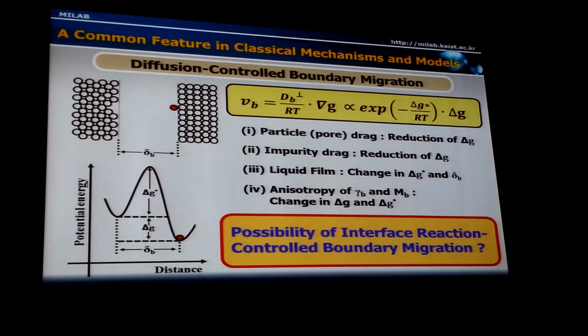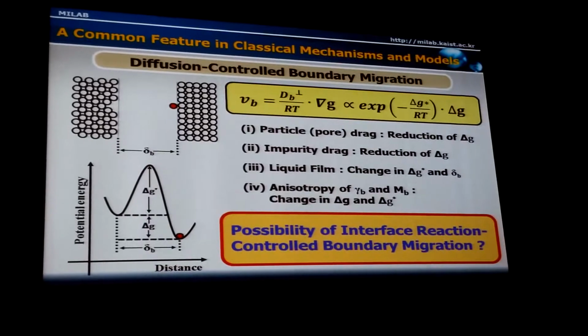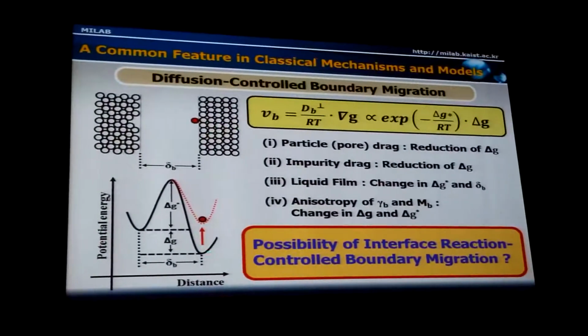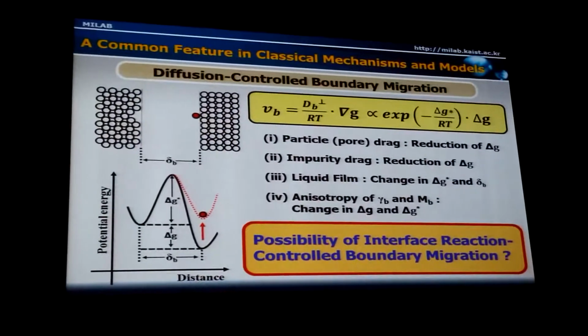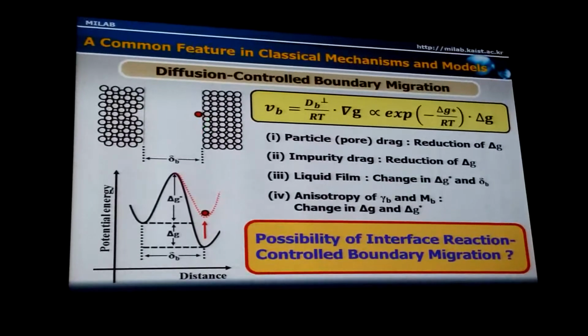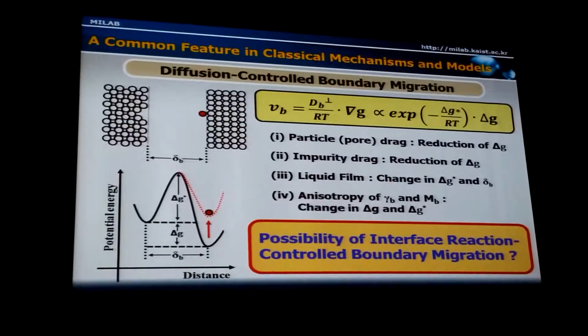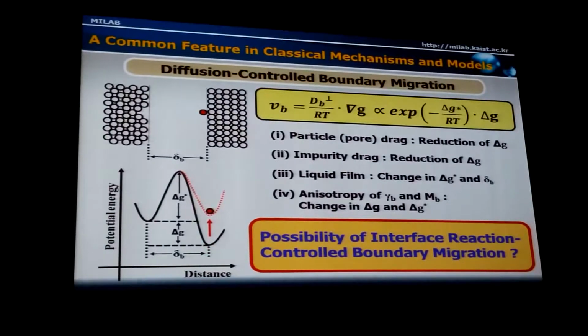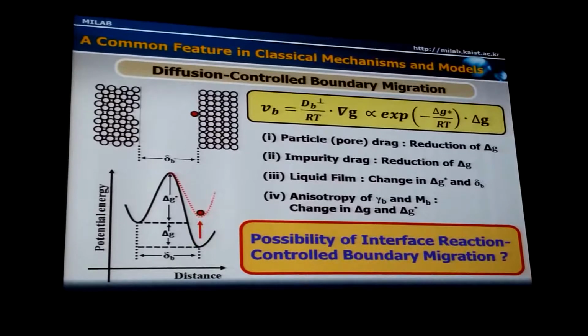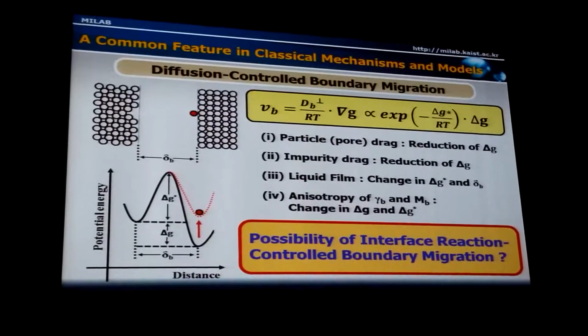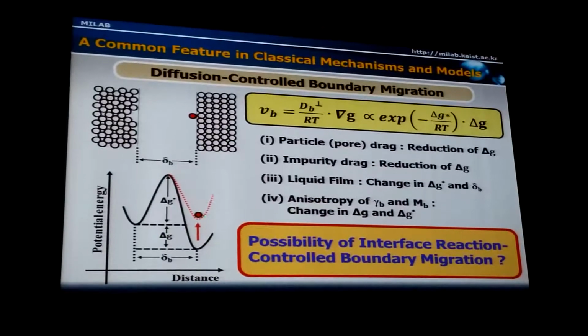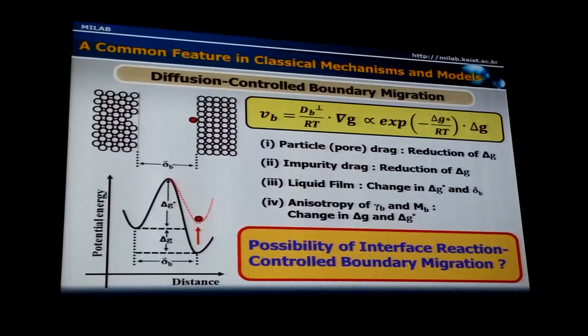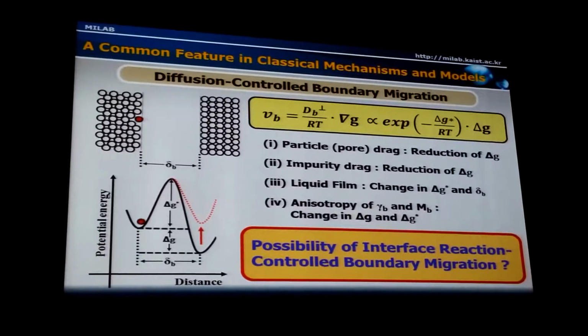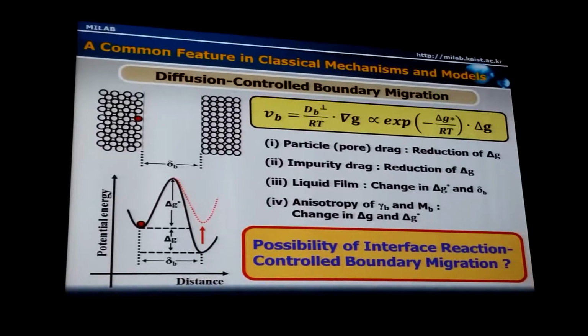Then, is there any possibility of interface reaction control of boundary motion? Suppose an atom transported from one grain to the other grain does not have the same free energy state, the same chemical potential, as those already present in the other grain. For example, as schematically shown in this figure, it increases the activation chemical potential. Then the energy state of this atom can be larger than the driving force. In that case, the atom has a driving force to move back from the original site, exhibiting interface reaction control motion.